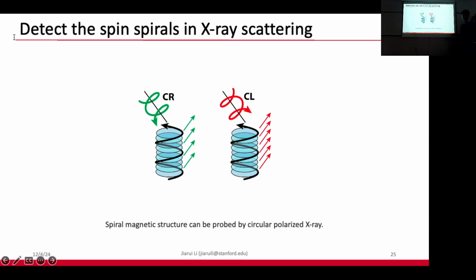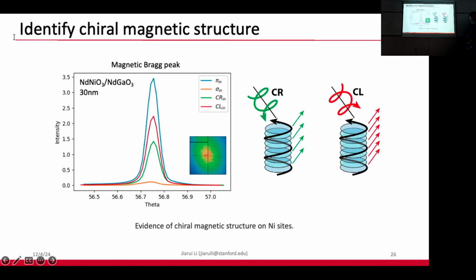And what we're thinking, from our perspective, is that these non-collinear magnetic structures can actually be probed by circularly polarized X-rays, because when you have a non-collinear magnetic structure, there exists a chirality in this magnetic structure. Say, for example, we can have a right-handed circular spiral magnetic structure, and we expect it to interact differently with circularly polarized photons in the diffraction process.